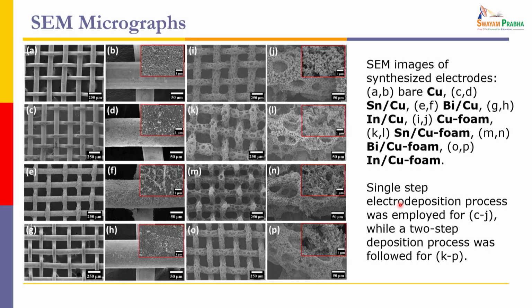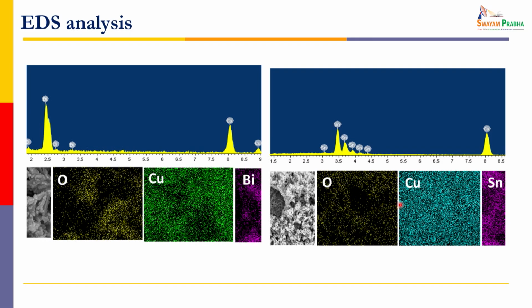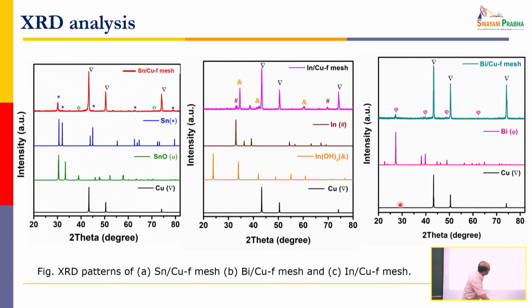These are some pictures to show, you have a copper electrode with different magnification. Then we have tin deposited, bismuth deposited, indium deposited. We have deposited three different materials on this copper foam, and we will be testing them for the electrochemical experiments. We also confirmed the presence of bismuth, tin and indium by EDAX analysis and also by XRD analysis. Here you can see tin is there, indium is there, bismuth is there, which are deposited on the copper foam we have.